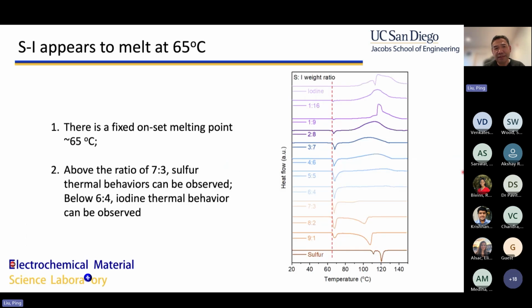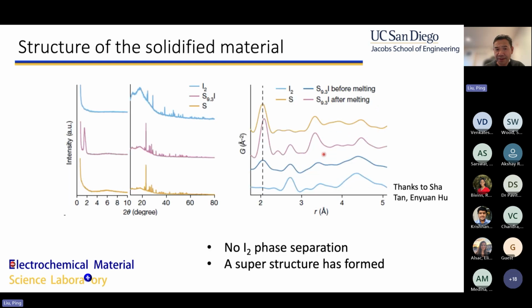So we did a lot of thermal analysis. We determined the melting point is 65. And then we use this type of series of ratios to determine what is the ideal ratio for the material. And then we freeze the material, to try to decide what did we actually make.